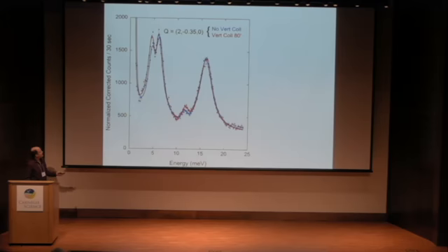All right. And again, this explains then why we see, when we vertically collimate the incident scatter beam, we're effectively amplifying any in-plane process, right? We're no longer integrating out of plane. And so this local mode intensity, shown here, actually gets larger relative to the optic mode, which I scaled to be the same.